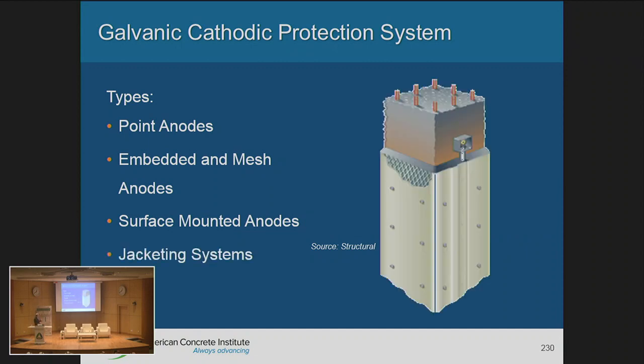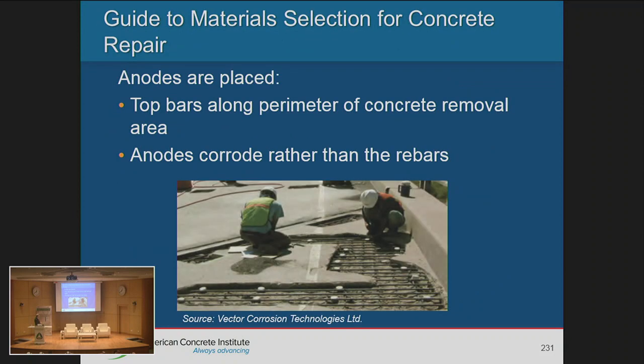Here's another jacketing system. It's the mesh with plexiglass for protection. Here we have this job where, as we talked about, you need to prepare your surface with straight or rectangular saw cuts. This is poorly done. You have too many corners, ins and outs. That is not properly done. You see those anodes placed all around the perimeter and the spacing between them. There's protection here, let's say 150 millimeters total, but in between there's nothing. And the bars inside that concrete are not protected.